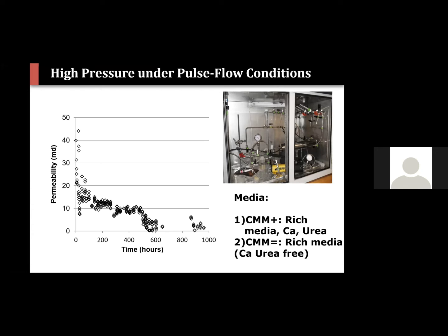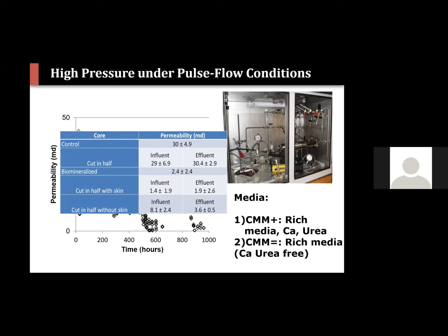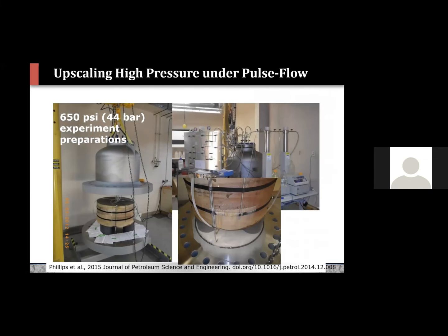They can withstand supercritical CO2, and they can effectively reduce the permeability. And this was a Berea sandstone that was used here. We generally see the permeability of the influent and effluent is broadly similar. There is a slight change, but ultimately we are avoiding inlet plugging by this pulsed injection strategy.